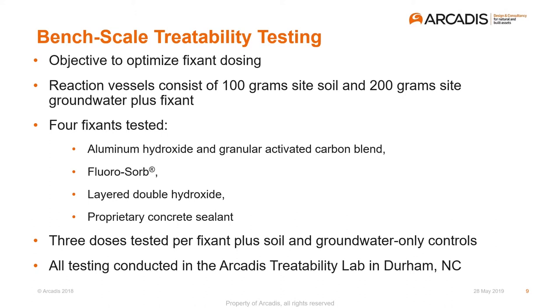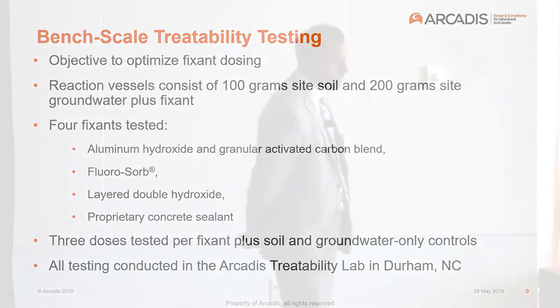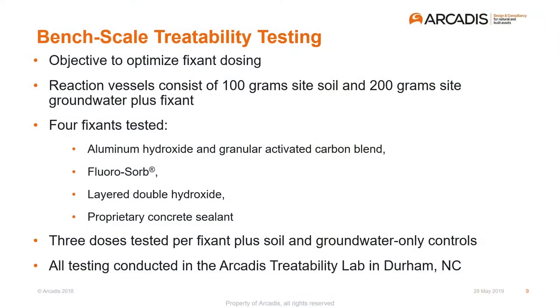Another was a proprietary product that is a combination of aluminum hydroxide and activated carbon. A layered double hydroxide, which is a layer of hydroxides designed to basically suck PFAS into the individual layers and supposedly, per the literature, perform very, very well for PFAS adsorption. And the last was a proprietary concrete sealant, which was a stretch. It was not intended for this purpose, but in the name of science. 3 doses were tested per fixant, and we ran some controls, and all the work was done in our treatability lab in Durham with the analysis done commercially at SGS Axys.